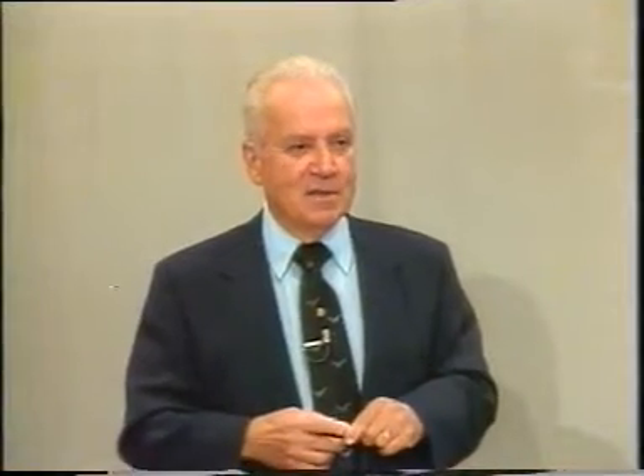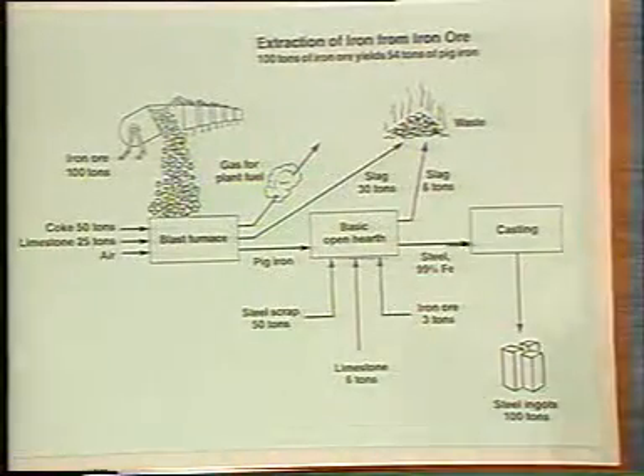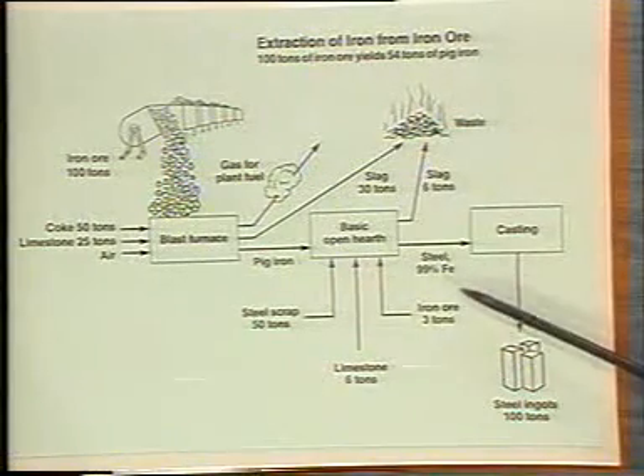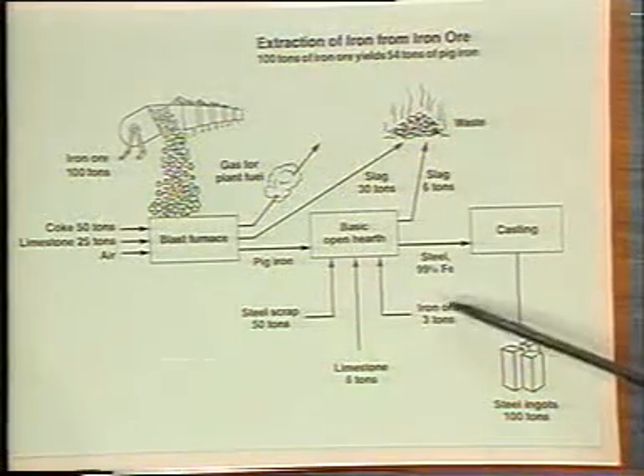We'd open the oxygen tank, and as the oxygen would run through, it would see the iron and oxidize the iron. And the heat of oxidation of iron is tremendous. It's so hot that it would melt the bricks in front of it, and we could melt a hole in it. So now you could stand a long way back and fish this pipe up there and melt the brick, and then the whole cascade of 200 tons of iron comes rolling out of the furnace, and you've got to catch it in something. And so what we do is we catch it in a teaming ladle, which we'll look at, and we can get iron that's very pure to come out of the material.